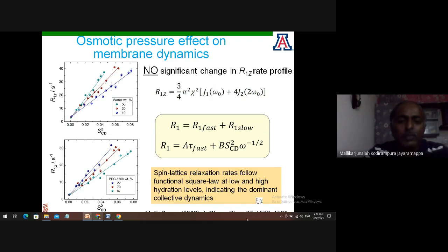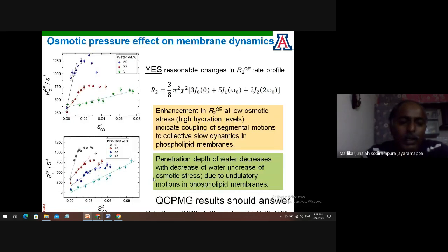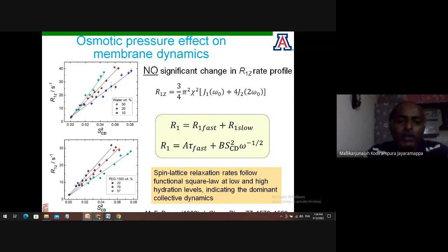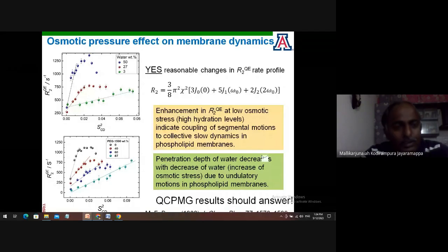As given at the bottom, the spin lattice relaxation rates follow a functional square law at low and high hydration levels, indicating dominant collective dynamics, in the sense of what type of motion is happening in our system. What we found is that we did not see much variation in the R1Z measurements, that is, the spin lattice relaxation measurements, as I increased the water concentration. But whenever I did spin spin relaxation measurements, where slow motions can also be measured effectively, we started seeing that it deviates from the linear fit. Whenever the order parameters are increasing, they deviate from that. That tells us that the penetration depth of the water decreases with decrease in water due to undulatory motion.